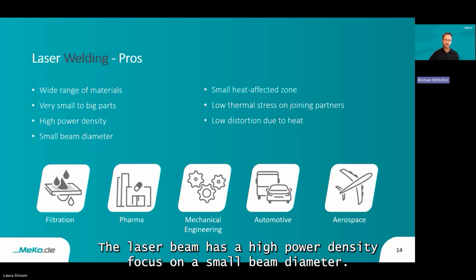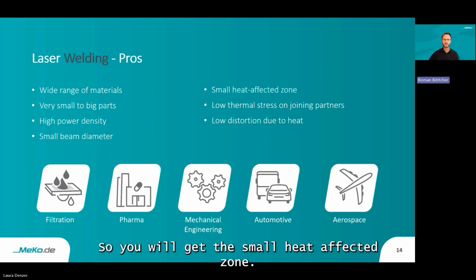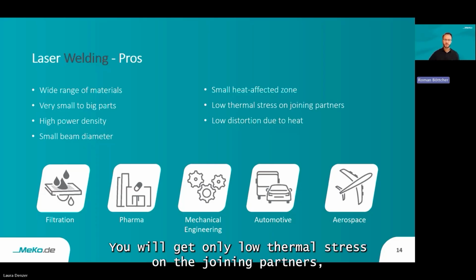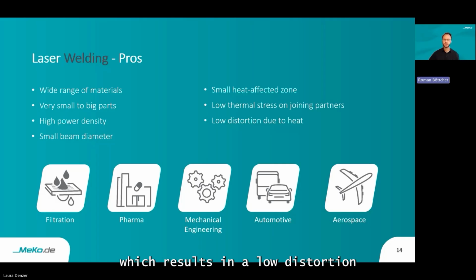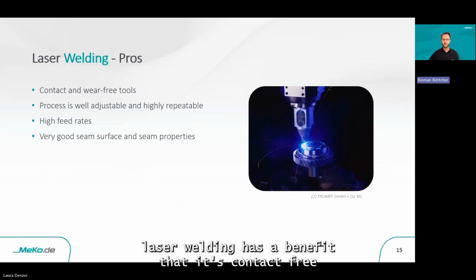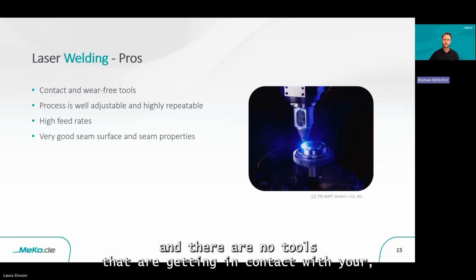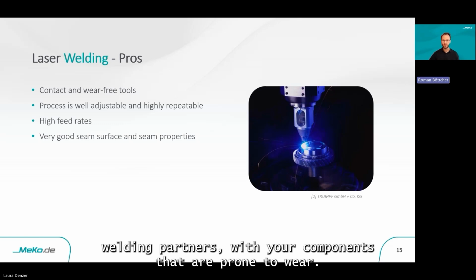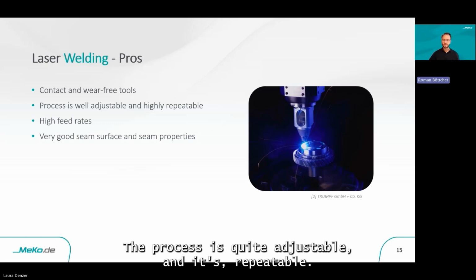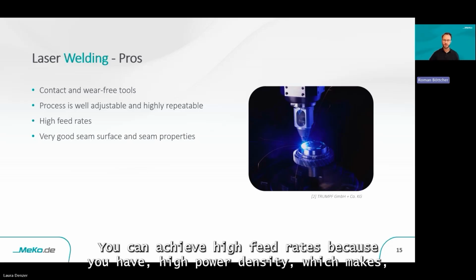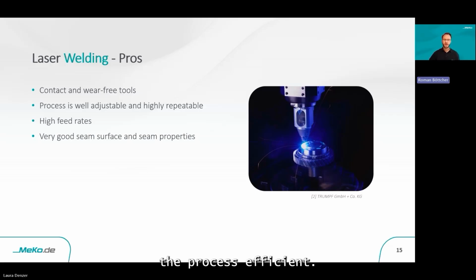The laser beam has a high power density focused on a small beam diameter, so you will get a small heat affected zone. You will get only low thermal stress on your joining partners, which results in a low distortion due to heat. Looking from the process side, laser welding has the benefit that it's contact-free, and there are no tools that are getting in contact with your welding partners, with your components that are prone to wear. The process is well adjustable and it's repeatable. You can achieve high feed rates because you have high power density, which makes the process efficient. You will get good seam surface and seam properties, so oftentimes you can reduce the amount of work in post-processing.